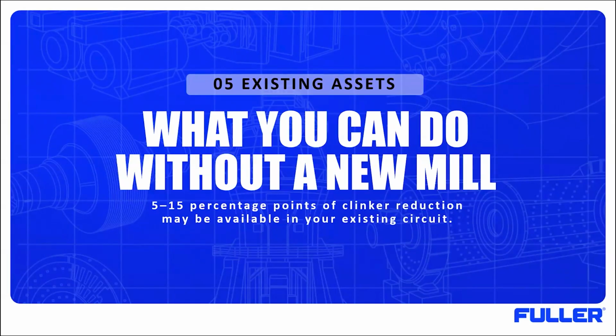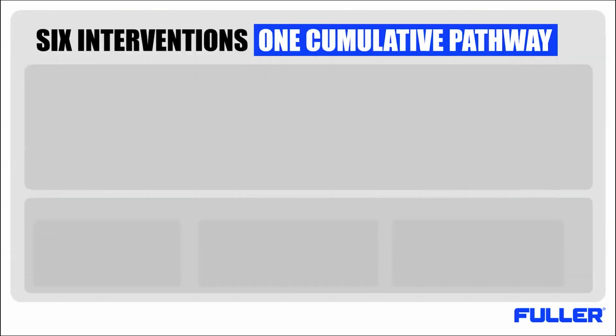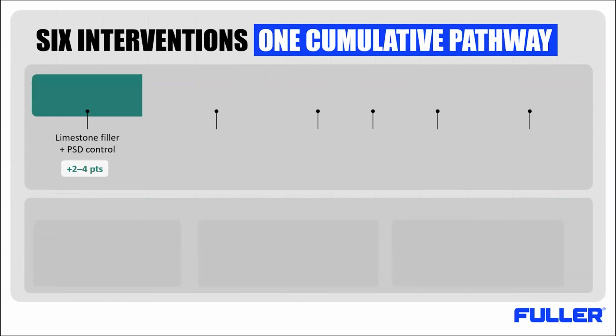Many plants still have clinker reduction potential inside the current system. Clinker reduction is usually not one big move. It's a cumulative pathway where several smaller improvements can work together. For example, limestone filler combined with better PSD control may allow around 2 to 4 percentage points of clinker reduction.